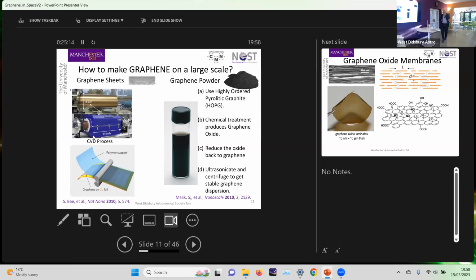What you do is you put some graphite into a chemical bath, a very strong oxidizer, sulfuric acid and potassium permanganate. And what it does is it pops chemical groups, OH groups in this case, between the layers. To do that, the layers are forced apart, and because the layers are forced apart, they're bonded less strongly together.